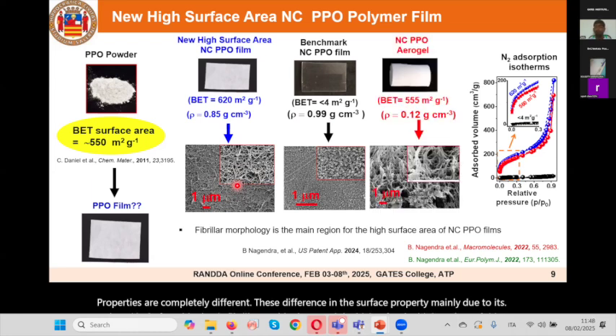And another important observation: compared to aerogels, our film shows a very high surface area. Till now, aerogels were known to have the highest surface area, 550. But our film surpasses their surface area, more than aerogel and powder. So this kind of film with these surface functional properties is completely new. For this method, we recently filed a US patent, and it has also appeared in some important publications.